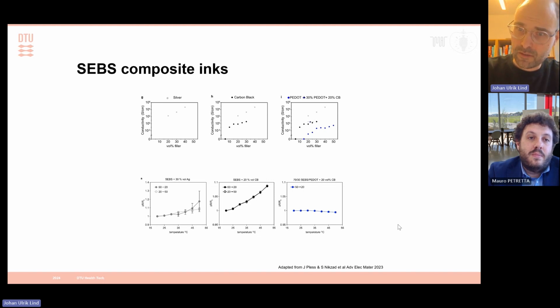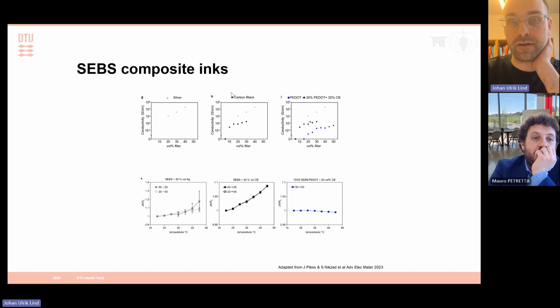So, for instance, for this SEBS-based system, which has been published actually quite a bit using other approaches, we found that the silver composites were significantly more brittle than, say, the carbon black particles. And that's also true if you add graphite particles. And that kind of highlights in our view that the binding between the particles and the matrix is key.